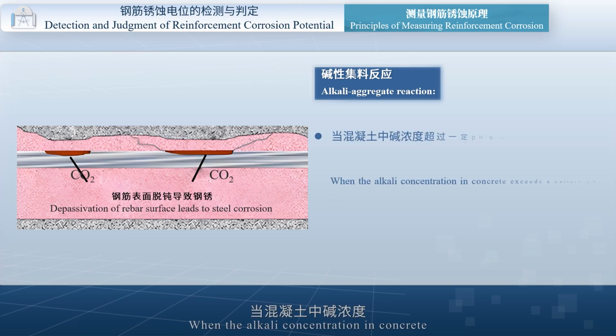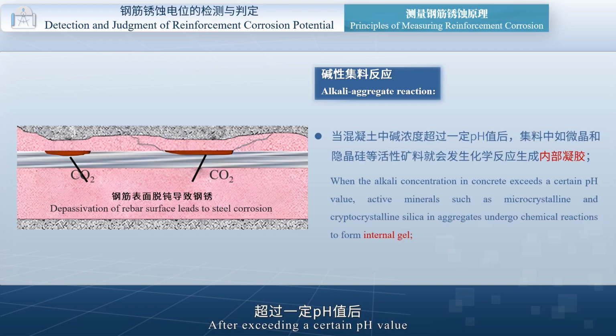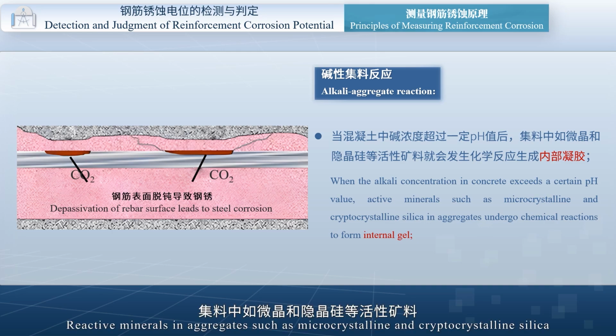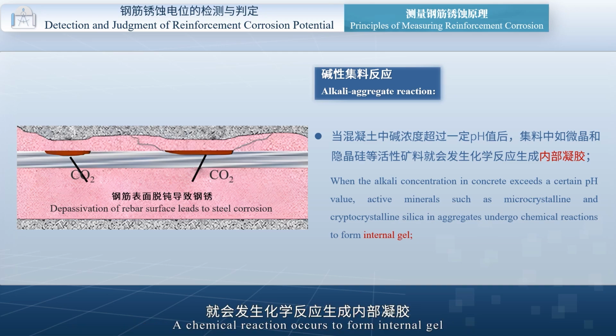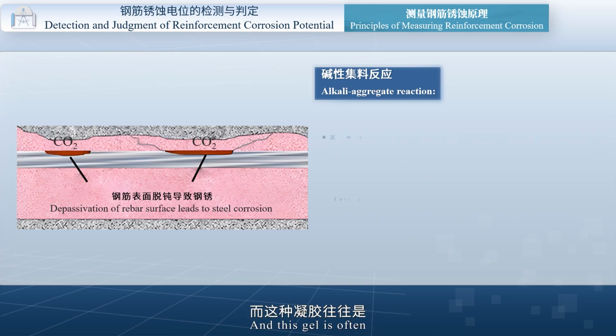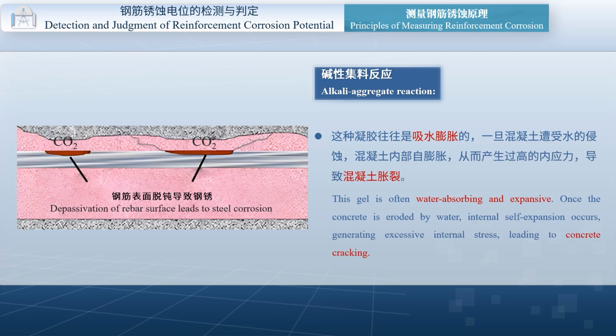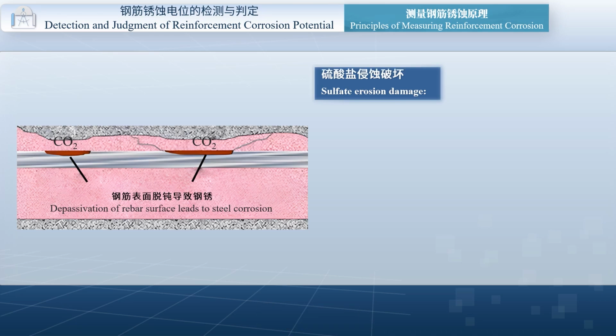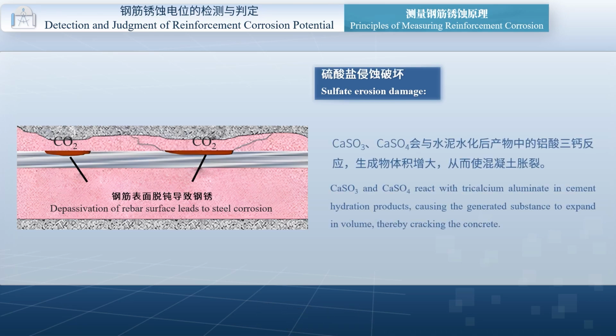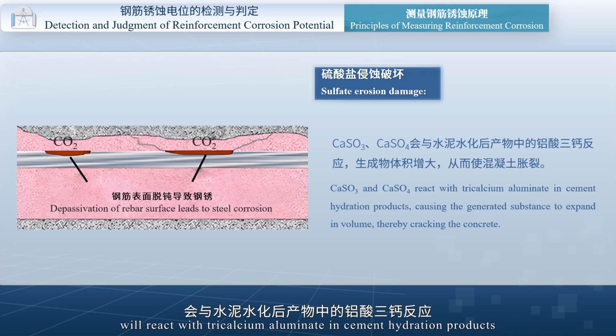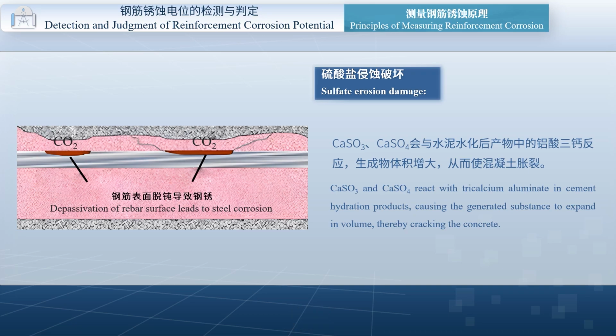Alkali aggregate reaction: when the alkali concentration in concrete exceeds a certain pH value, reactive minerals in aggregates such as microcrystalline and cryptocrystalline silica undergo a chemical reaction to form internal gel, and this gel often absorbs water and expands. Once the concrete is eroded by water, internal self-expansion of concrete generates excessive internal stress, causing concrete expansion cracking. Sulfate erosion damage: calcium sulfite and calcium sulfate will react with tricalcium aluminate in cement hydration products. Volume increases, thereby causing concrete to crack.